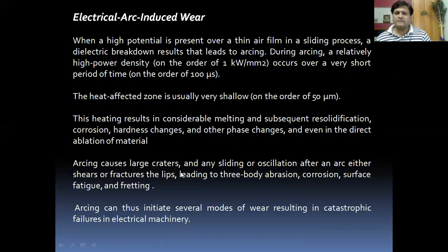Arcing causes large craters, and any sliding or oscillation after an arc either shears or fractures the lips, leading to three body abrasion, corrosion, surface fatigue, and fretting. Arcing can thus initiate several modes of wear, resulting in catastrophic failures in electrical machinery.